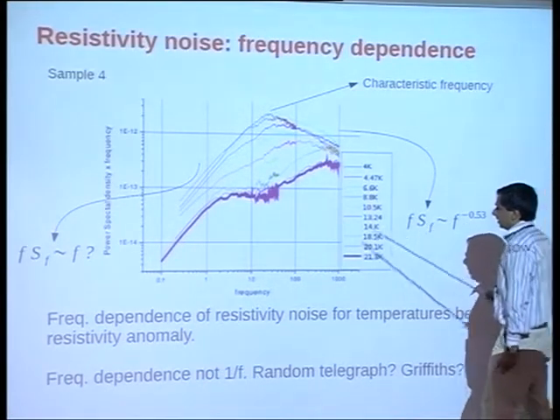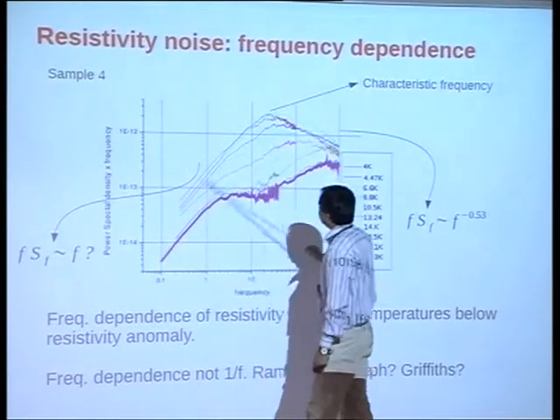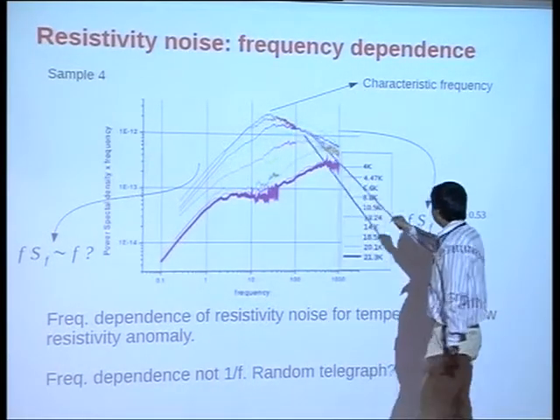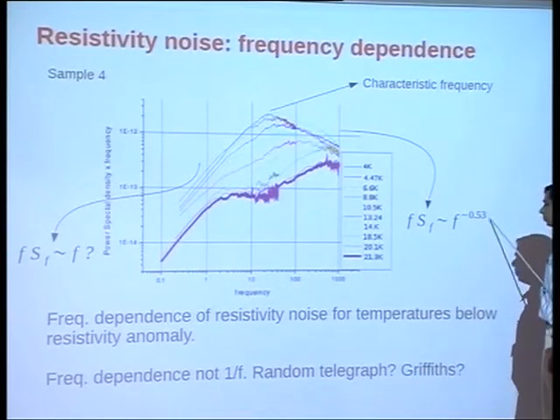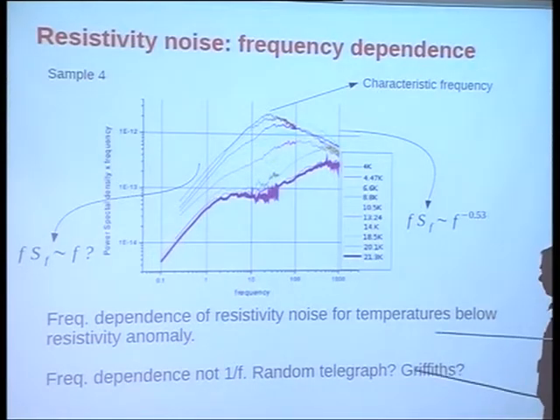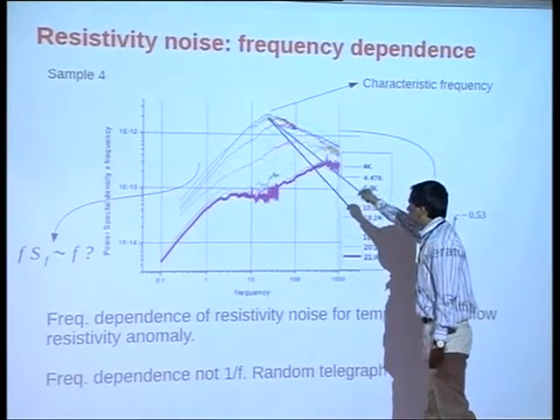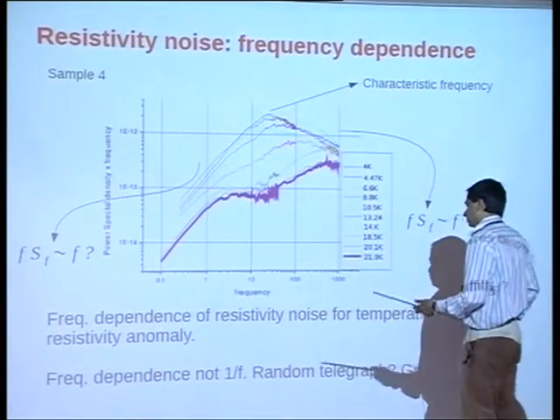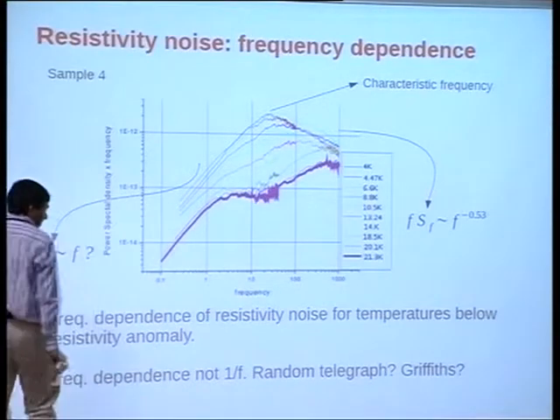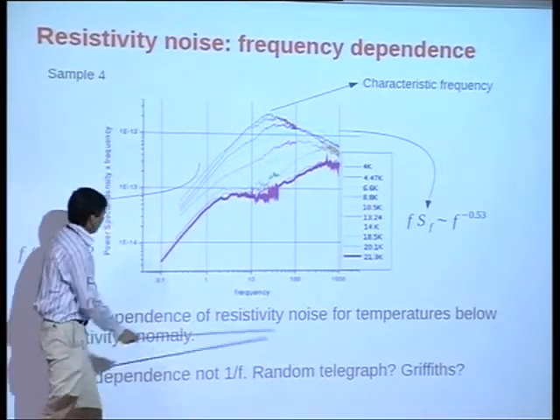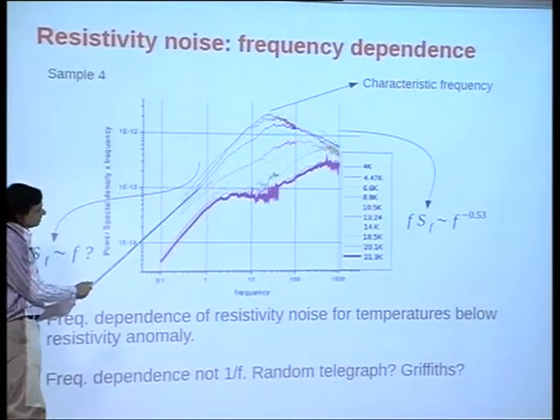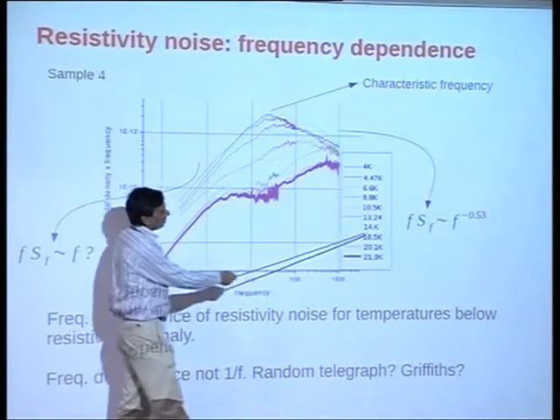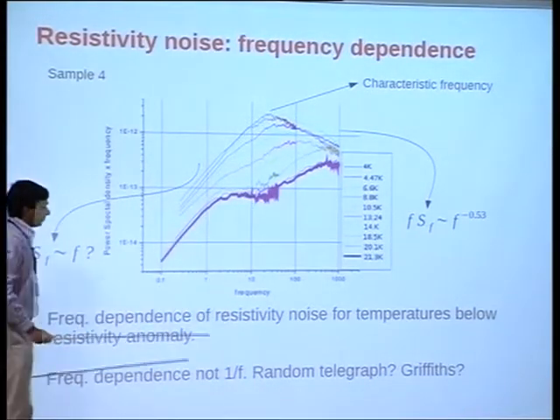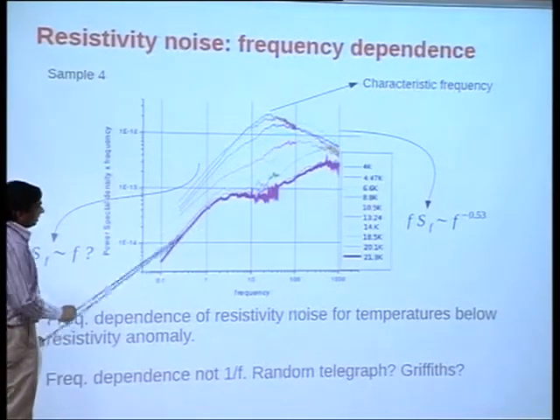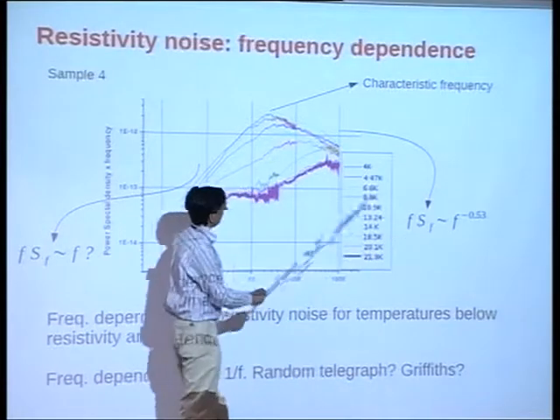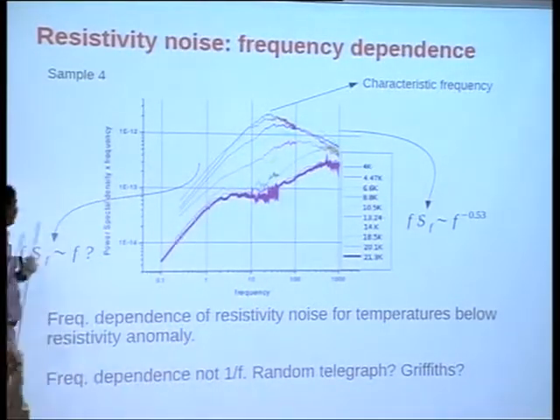At low frequencies, this function goes roughly linearly in F at low temperatures, and at high temperatures, it looks like F to the power of minus 0.5. Okay, so the characteristic frequency is around 13 hertz, and it's not a 1 over F dependence. Our first suspicion is, shall we try a random telegraph? That will go linearly with F at low frequencies. At high frequencies, it should have gone like 1 over F, but we don't have that here. And Griffiths, on the other hand, because of the stretched exponential relaxation, should actually go like F to the power of minus 0.5 at high frequencies, but then Griffiths is not really relevant for high frequencies, right?